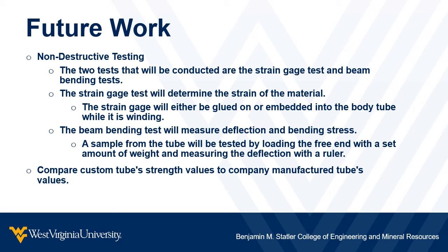For non-destructive testing, the 2 tests will be the strain gauge test and the beam bending test. The strain gauge test will determine the strain of the material. The strain gauge will either be glued on or embedded into the body tube while it is winding. The beam bending test will measure deflection and bending stress. A sample from the tube will be tested by loading the free end with a set amount of weight and measuring the deflection with the ruler. Finally, we are going to compare our custom tube strength values to the company manufactured tubes values.